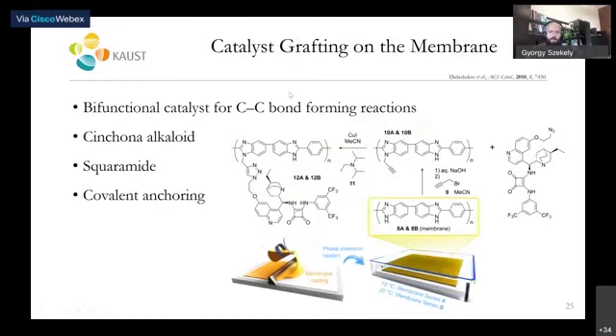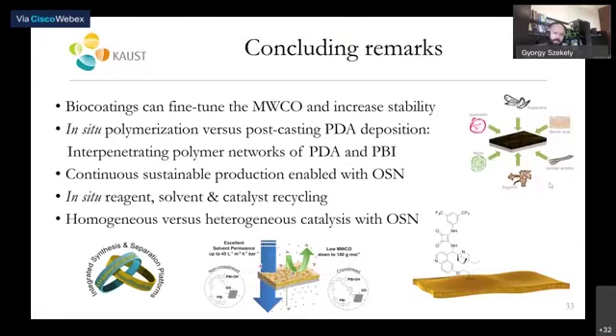So again, we turned to polybenzimidazole, and we looked at how to prepare robust membranes that you can employ in organic solvents or extreme pH, very low pH or very high pH. And we looked at polydopamine, which is derived from dopamine, and we looked at other naturally occurring materials to be able to achieve these high stability membranes. We also looked at another example where we used GO, graphene oxide, to increase the stability of the membrane and increase the permeance of the membrane, and the last example showed how we can incorporate a traditional organocatalyst covalently linked onto the polymer substrate, and then use this membrane in a catalytic membrane reactor where you can do the catalysis